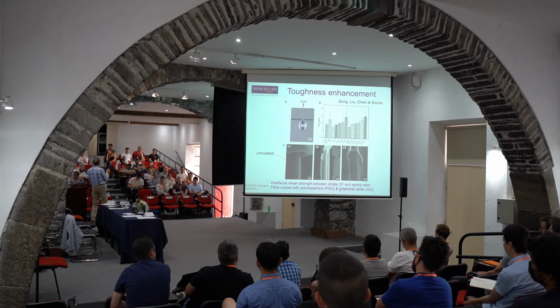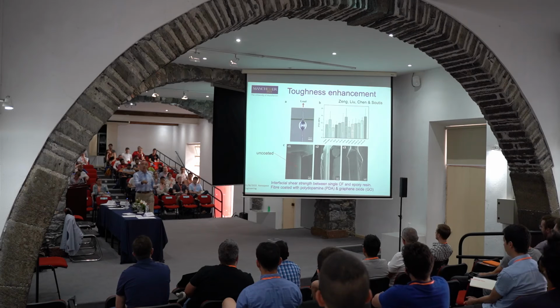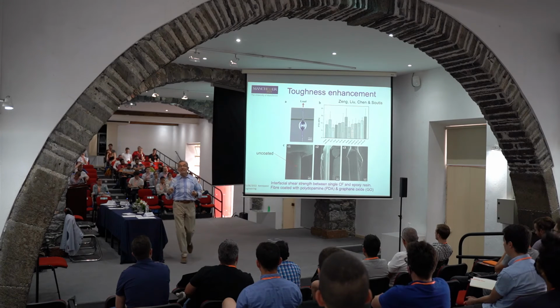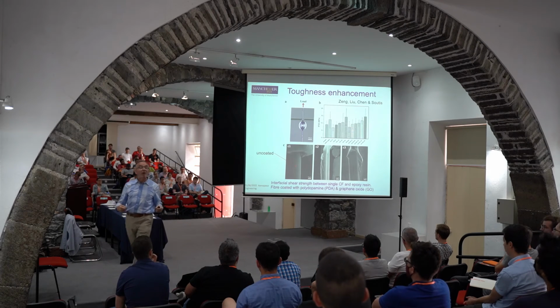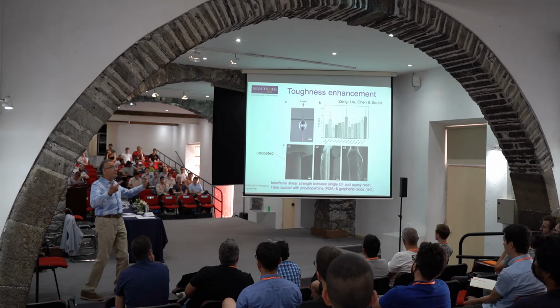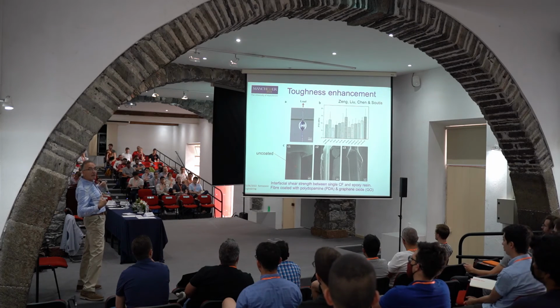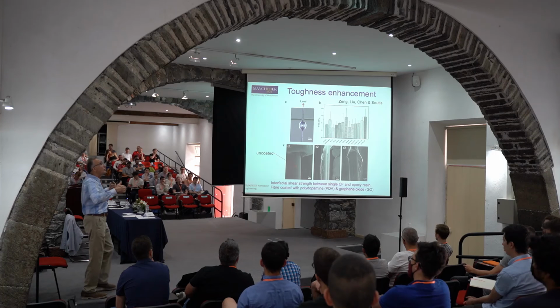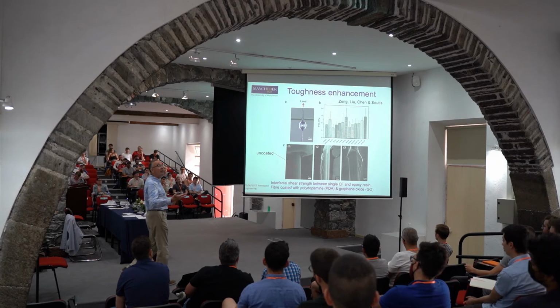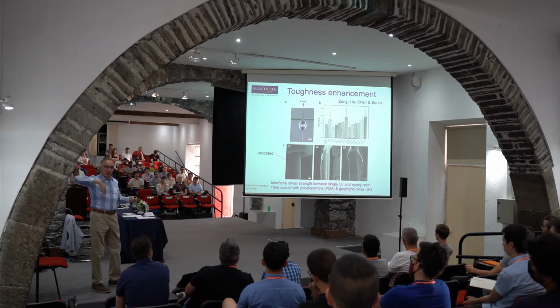Because you remember, those micro cracks start at that kind of level, at that micro level. The fiber debonds from the resin. And here you can see an uncoated fiber on the left-hand side and a coated fiber, where in order to pull out that fiber from that block of resin, you require to dissipate more energy. It's much harder to get those micro cracks that we've seen earlier. It's not anymore at 0.3 or 0.4 or 0.5% strain, it's probably at 1% strain.